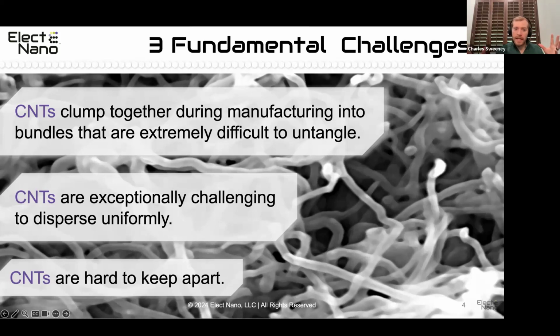Even if you do manage to get them untangled, nanotubes are really hard to keep apart and keep well dispersed in these systems, because their surface energies are very different typically from the composites that we're trying to put them into. And so I would say the vast majority of literature and many companies that operate in this space have tried to take reactor carbon nanotubes, sonicate or high shear mix them into a system, and then make a concentrate or dilute it down, study its properties, look at it under a microscope, and then so many times in literature I've seen the conclusions: better dispersion is likely needed in order to fully realize the modulus improvements or the toughness improvements or the electrical properties.